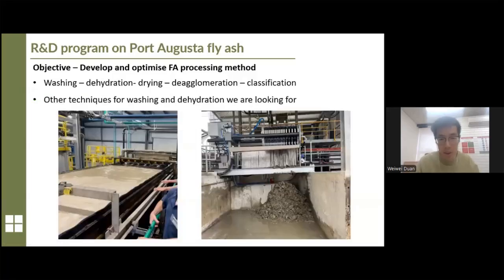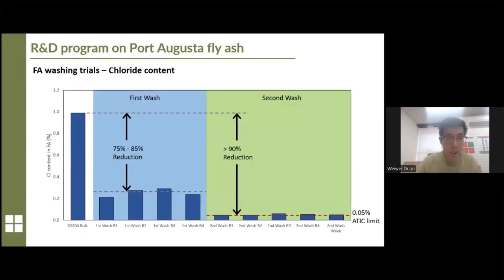Okay, and in addition to the equipment we currently use, we're also looking at other chloride washing techniques and also dry techniques. So that's some of the results of the chloride washing. After 2 washes, we can get a 90% reduction of the chloride from the original bulk sample to around 0.05, which meets the ATIC limit.